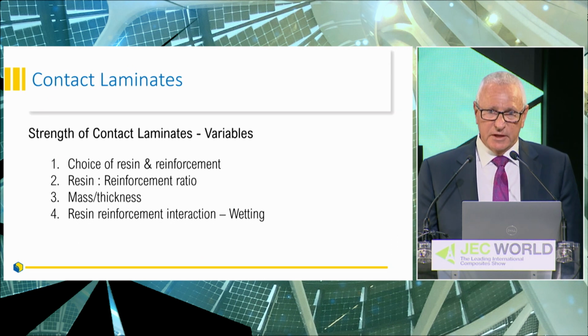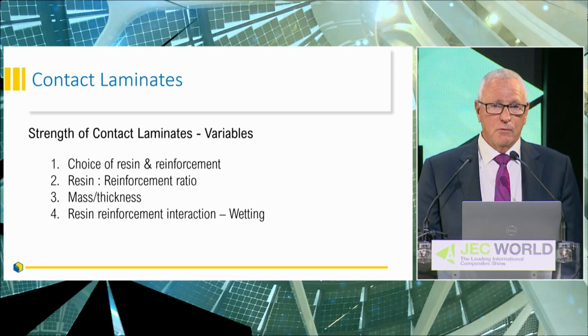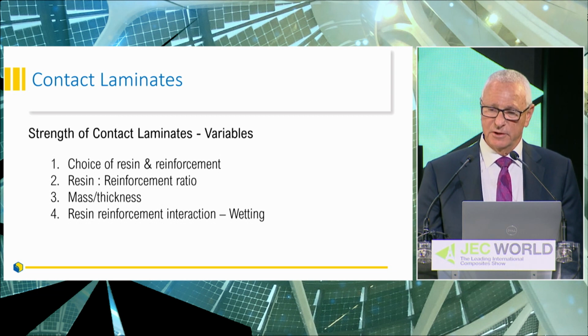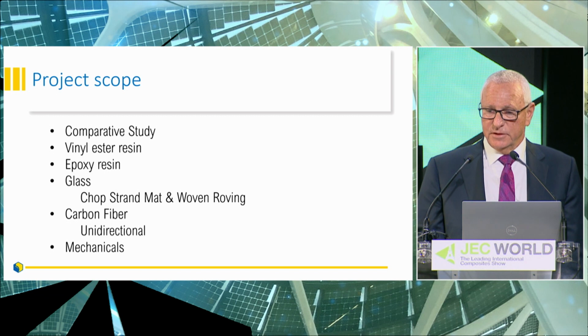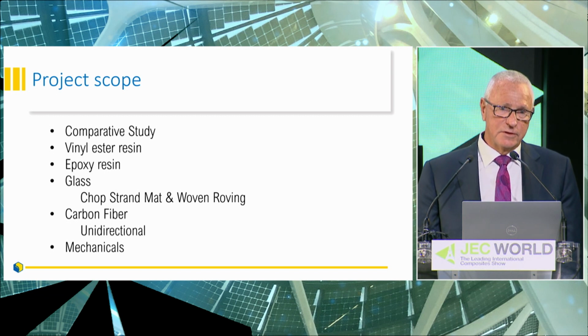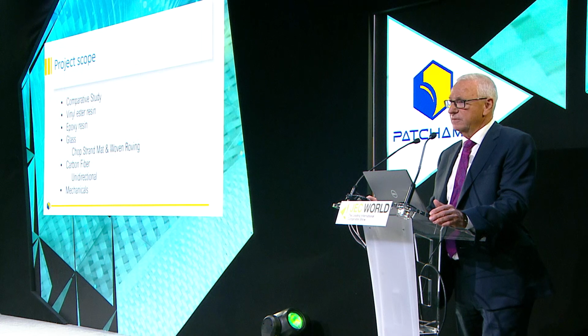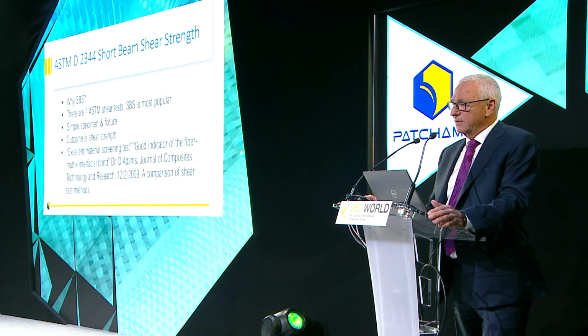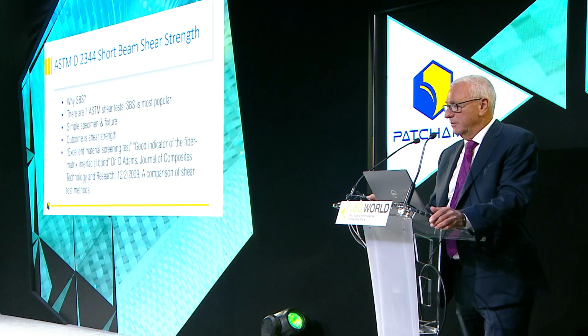So there's a lot of variables when you're making contact laminates. Number 4 on that list is really what we were interested in, and that's the interaction between the resin and the reinforcement, or the wetting of the reinforcing fibers. This particular one, we used the vinyl ester. We did vinyl ester glass, and we did vinyl ester carbon fiber, and we did epoxy carbon fiber. We didn't do any epoxy glass on this one. And we did focus primarily on short beam shear, the D2344 short beam shear.